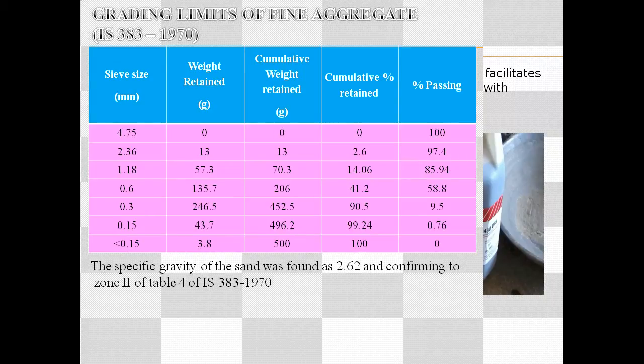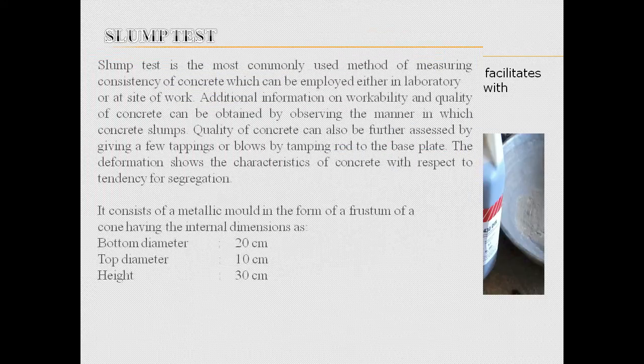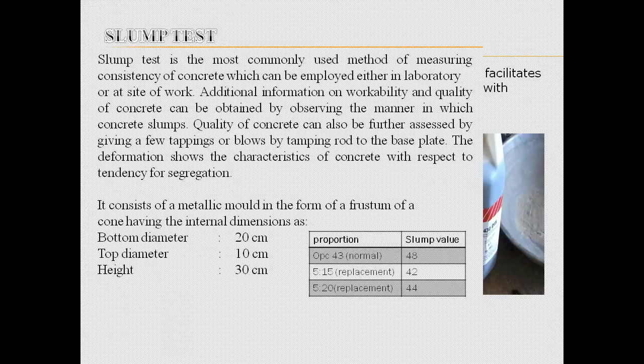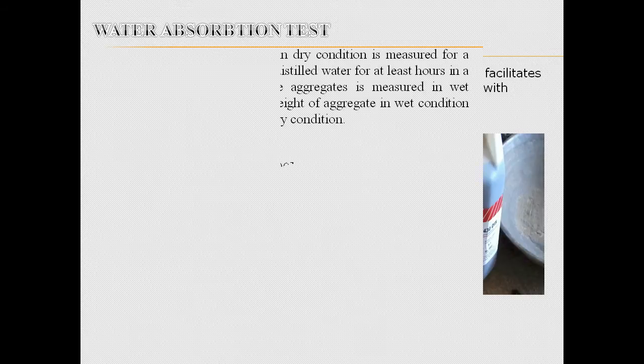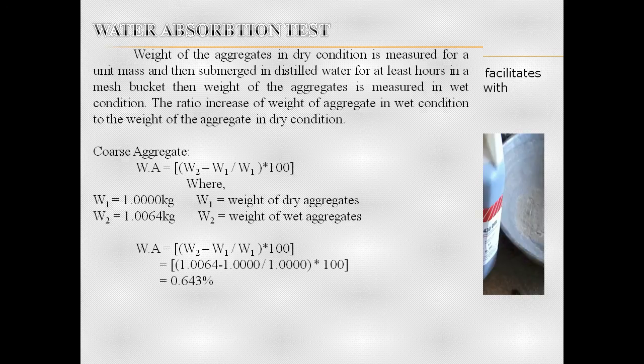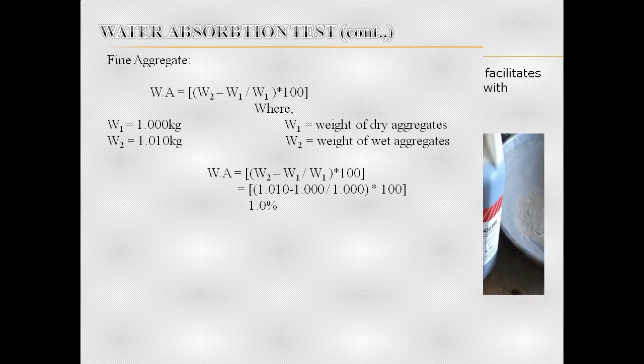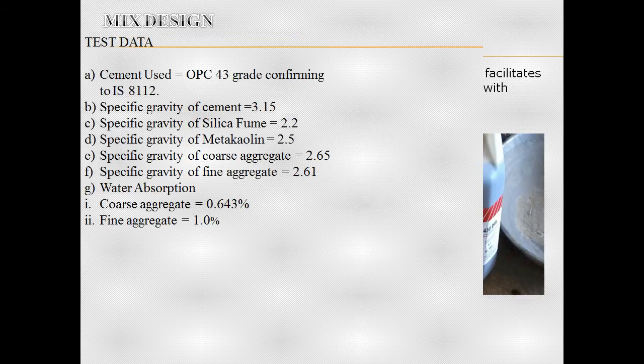Next, we are grading the limits of fine aggregate according to IS 383 of 1970, and it was found to be conforming to zone. Next, we are doing the slump test using the slump cone, and we found all the slump values to be less than 50 mm. Next is the water absorption test, which is done by wetting the coarse aggregate, then drying it, then finding the amount of water absorption in the coarse aggregate and fine aggregate. In coarse aggregate, the water absorption was found to be 0.643%, and similarly, for the fine aggregate, it was found to be 1%. So next is the mix design which we have followed.